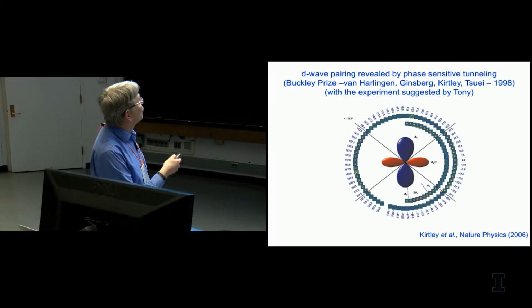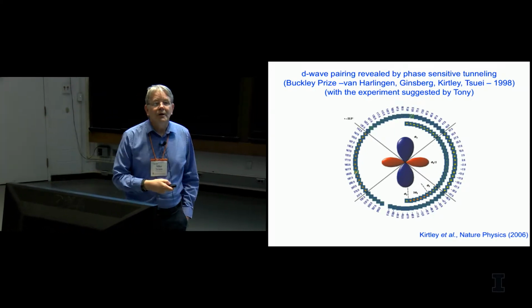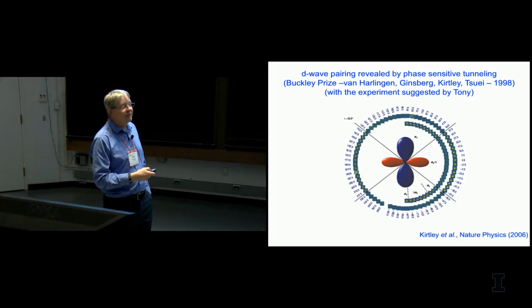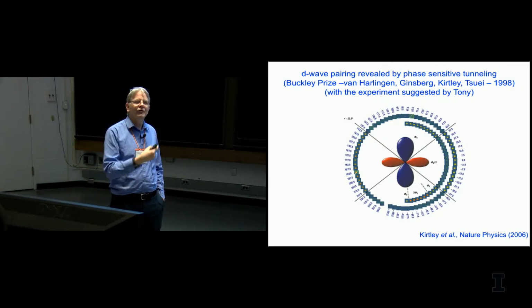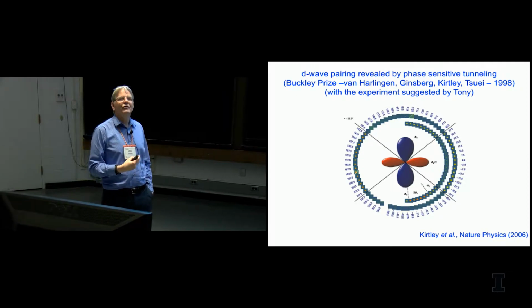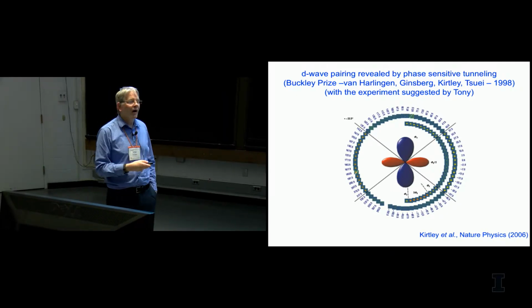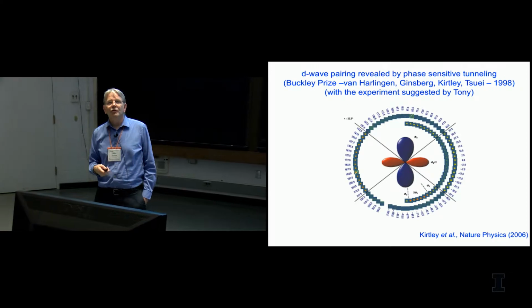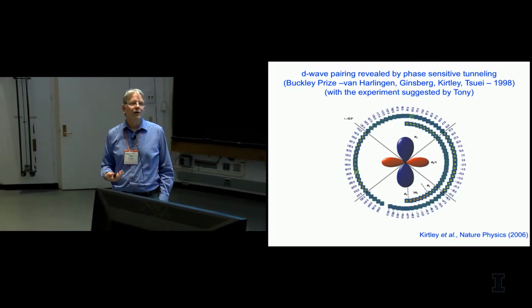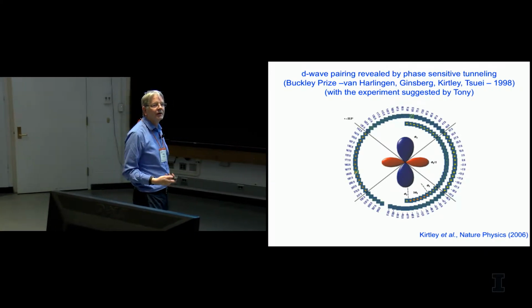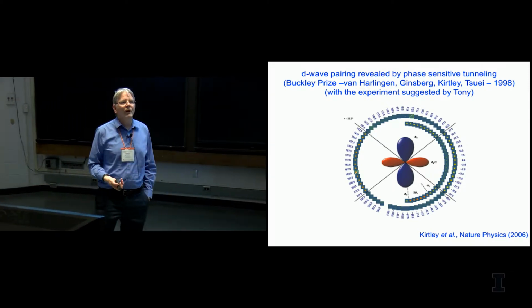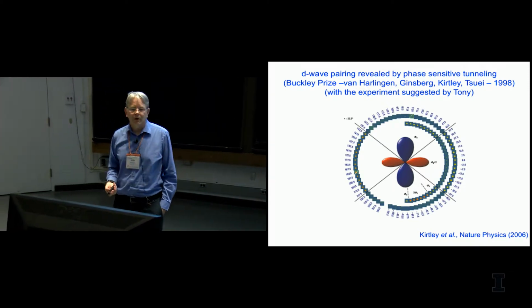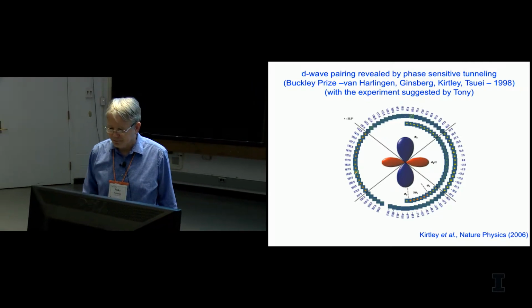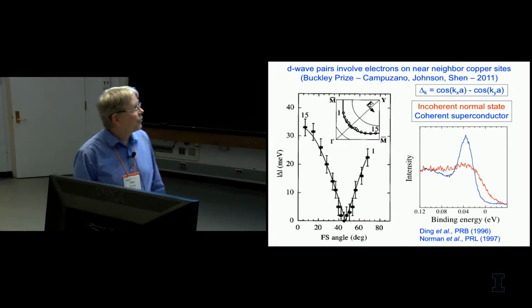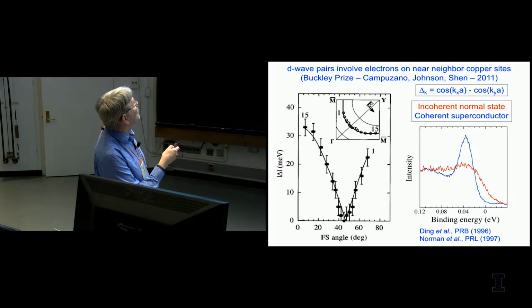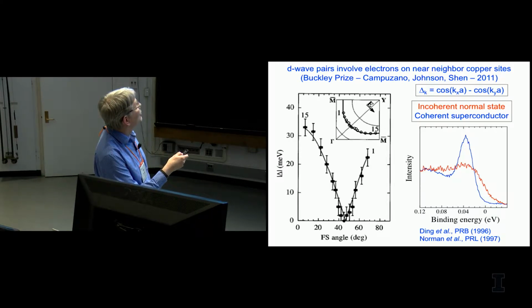And as far as we know, this is a pretty innocuous superconductor. It behaves in a BCS-like fashion. So if you look at the phase diagram, it's actually the superconducting phase which is the least anomalous phase, and there are the phases that surround it, which are the most anomalous, which is of interest, right, because superconductivity is an instability of the normal state. So if you want to understand the origin of the superconducting phase, you need to understand the origin of the normal phase from which it emerges. There are a few other things that we know, and one of them is that the d-wave pairs involve electrons on near-neighbor copper sites.